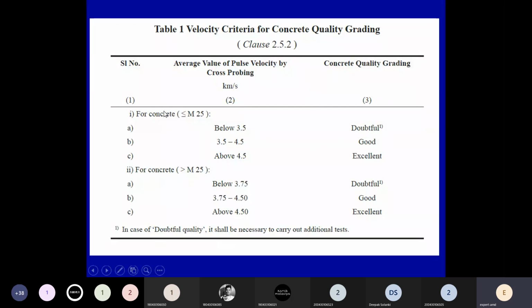The first category is for concrete less than or equal to M25 grade of concrete, this is the criteria. If your value is below 3.5, your concrete is under doubtful category. If it is 3.5 to 4.5, it is good. So good is acceptable. Above 4.5, the quality is excellent. For concrete greater than M25, below 3.75, doubtful. 3.75 to 4.5, good. And above 4.5, excellent.